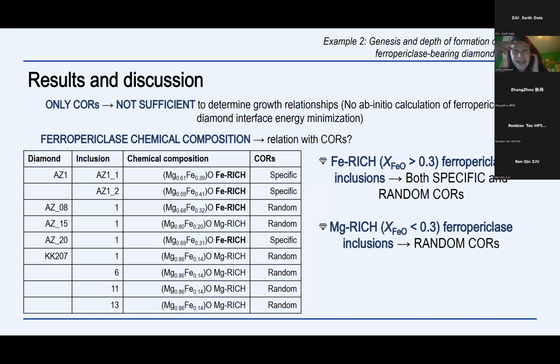Unfortunately, the answer is no, because for the ferropericlase-diamond system, at this moment, we don't have an ab initio calculation that allows us to predict how ferropericlase and diamond interact to minimize the interface energy. But considering that ferropericlase inclusions within diamonds can present very different chemical compositions, we suppose that the development of different types of CORs between the two minerals can be correlated to the chemistry of these minerals. And in order to understand this, we determined the chemical composition of some ferropericlase inclusions that we analyzed